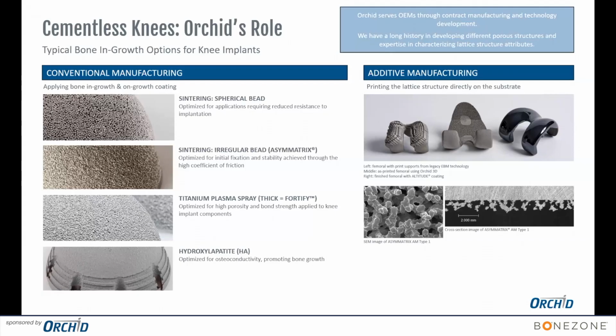modality, right? And the advantage of additively creating not only the implant itself, but printing the lattice structure integrally during the printing process is the fact that all of the limitations related to either sintered or plasma spray coatings are completely eliminated. Right? So an example for plasma spray, it's a line of sight process. The size of the beam is about 12 millimeters, half an inch or so.